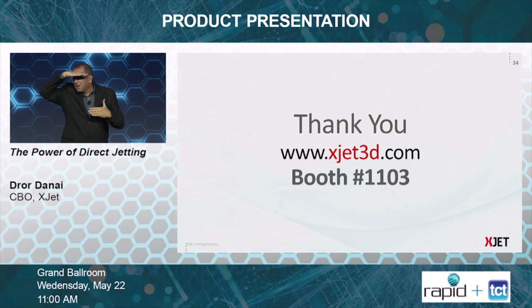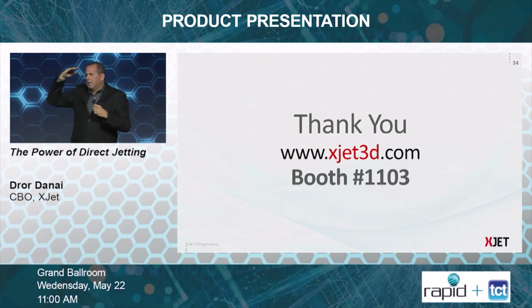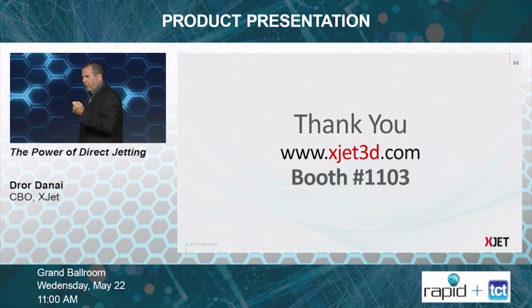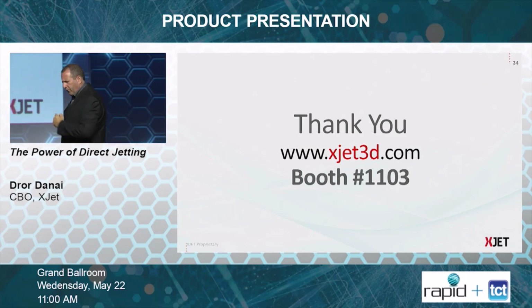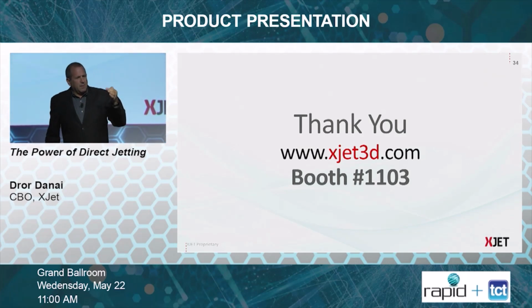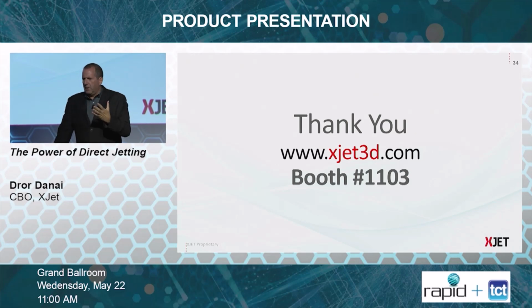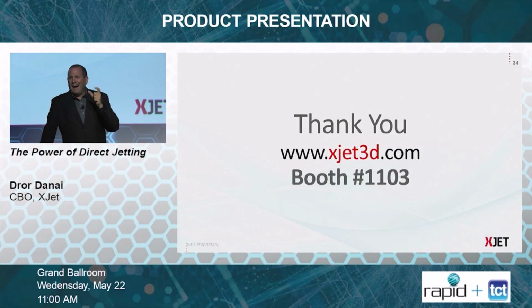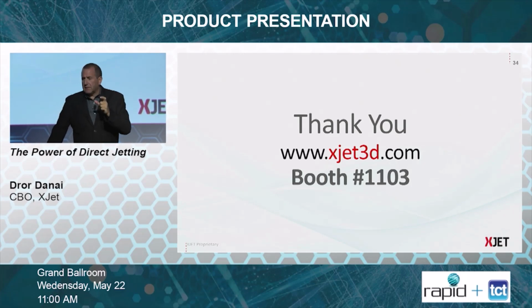Yeah, hi. I just want to know what the material strength looks like after printing. Okay, the strength. I don't know if it was clear enough in the movie, not all of you were there. The part comes as a green part, but because there's so much less binder, it's already better than metal injection molding, for example, or ceramic injection molding. After sintering, and this is a big claim, the mechanical properties that are now being tested by our own users are identical or almost identical to the mechanical properties of the real material.